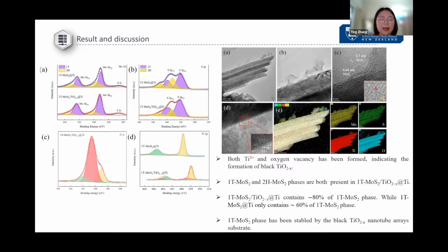From the analysis of the XPS result, we make the conclusion that the MoS2 nanosheet decorated on the black titanium dioxide substrate contains 80% of 1T phase, but the MoS2 nanosheet decorated on the titanium substrate only contains 60% of 1T phase. That means the decoration and the help of the black titanium dioxide can enhance the active 1T MoS2 phase in the MoS2 nanosheet. We also find the oxygen vacancy peak here and the titanium 3+ peak here that demonstrate the formation of black titanium dioxide.